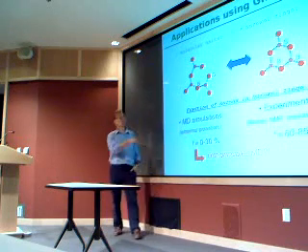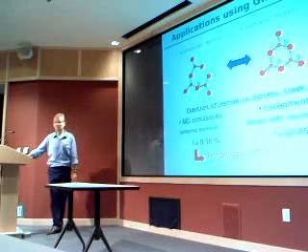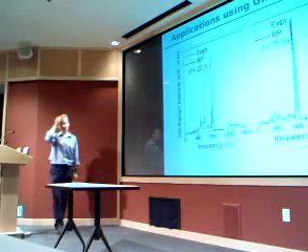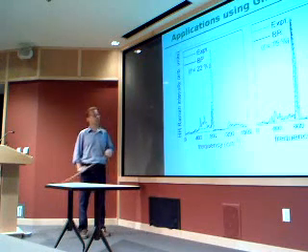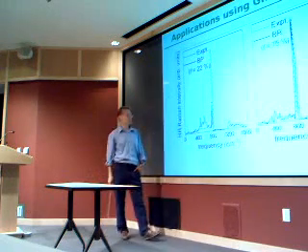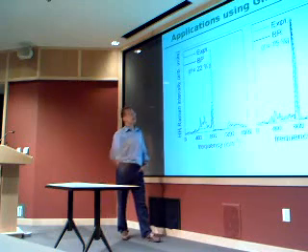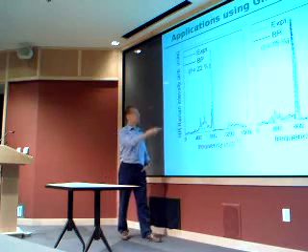So we believe that this is true. We showed the stability favoring this kind of fraction of the boroxol ring over this, and then, still to compare with the experiments, or to prove it also to the referees, we did some simulations of the experimental observables. So we have here two spectra. The full line is the calculated spectrum, and the dashed line is the experiment from Raman experiments.